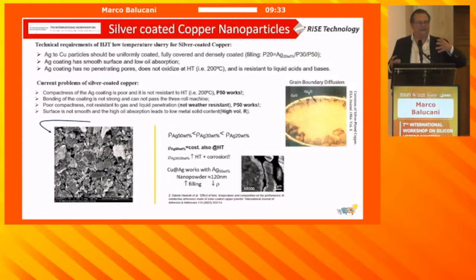This doesn't mean that it will not work. You will have an increase in resistivity. So that's why, if you take this nice paper, it shows that in principle everything works well if you keep the paste within 50% of silver quantity. So if the quantity of silver that you're keeping inside your paste is around 50%, and I'm seeing everybody, even Applied Materials, is around 43 or 44%, if that's the average, things work well.